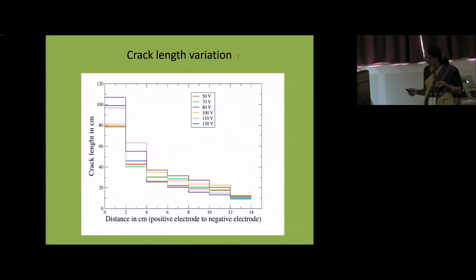And if we measure the crack length in each of the segments, and plot it like this against the distance between the positive and negative electrode, then we get something like this. The crack length is initially the largest, and in steps, the total crack length is going down, and there is also the effect of the varying voltage. For the lowest voltage, more or less we are getting the lowest step in each case, not exactly, but on average. And for the highest voltage, the steps are high. So this is our analysis of the pattern.